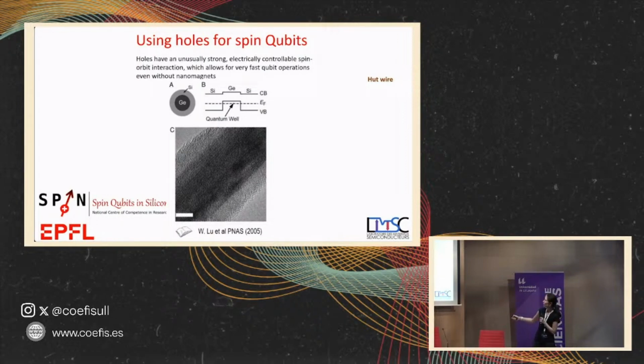So here you have the valence band, the conduction band, and you have germanium with a silicon shell. If you do this, the bands align in a way that you will always have a lack of electrons here, so you will have holes. These are positive charges in the nanowire. So you have here the germanium wire covered with silicon. And you have it for free, you don't have to dope. So these are materials that can have very high mobility and so coherence, and so they are perfect for quantum applications.